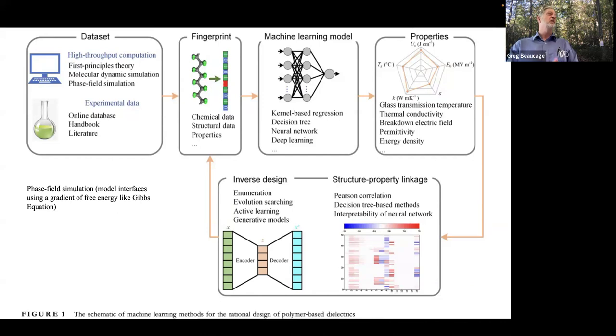What's going to happen is, instead of having a DSC to measure the glass transition and the melting point of your polymer, you're going to have some way to make an array where you can sample every possible combination of any possible polymer. To do that, automated synthesis machines exist. In the paper we'll look at, they have an automated block copolymer process, so we can make 2,000 samples in a day or a couple of days.